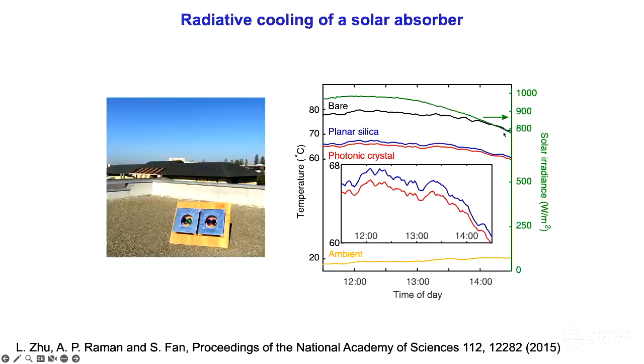We now, again, do our rooftop experiment under the sun, and you can see a very large temperature difference between the bare silicon structure and also the structure with silica on top of it. The difference comes from the radiative cooling effect. Moreover, the photonic crystal structure that we engineer has a temperature that's consistently lower compared with silica, and that comes from the ability to enhance the thermal emissivity coming out of the structure. So what we have created here, in fact, is a visibly transparent black body emitter for cooling purposes.